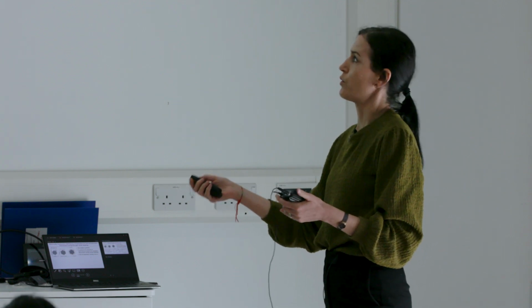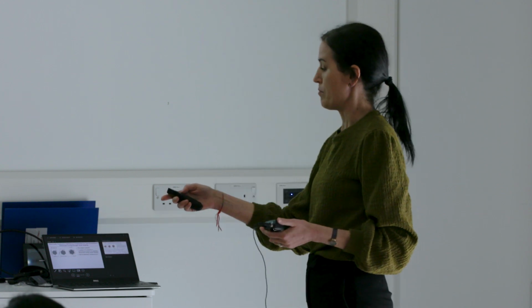And once we are above the percolation threshold, if we keep adding more and more conductive filler, we will be creating more and more conductive paths, and we will be developing this 3D electrically conductive network embedded into the polymer matrix. So this material is electrically conductive, and at the beginning of this project, we wanted to explore the potential of these electrically conductive nanocomposites for resistive thermoset curing through a Joule heating effect of this electrically conductive network of graphene incorporated into the polymer matrix in order to develop a novel out-of-autoclave curing method.